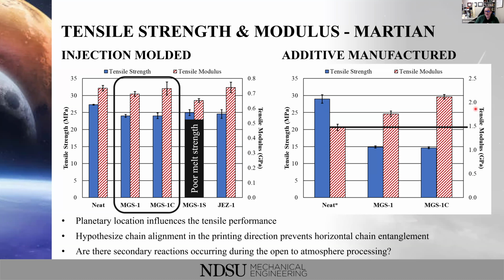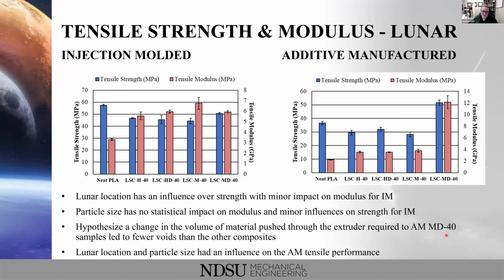The planetary location very much did influence our tensile performance. That tells us with Mars, at least, we need to be careful of where we're at on the planet, and think very carefully about how much regolith we put into that polymer, or what our expectations are of the mechanical properties or performance of that material. We also see some differences in the tensile strength, which isn't unheard of, and some differences in the tensile modulus as well. But based on observations of the additive manufacturing process, we believe there are some secondary reactions occurring in that open to atmosphere processing that are potentially hindering our mechanical properties in the end. We'll talk about that in just a little bit.